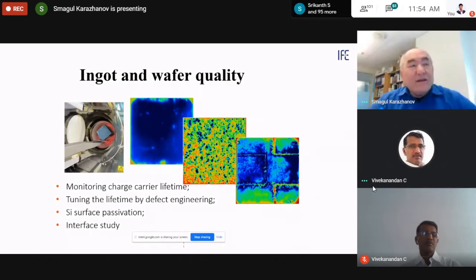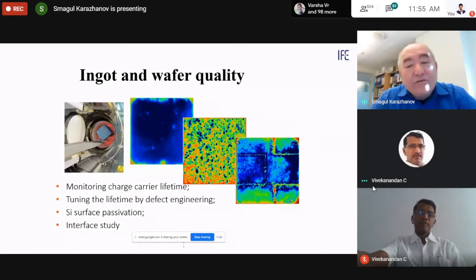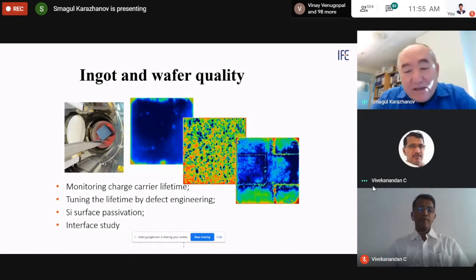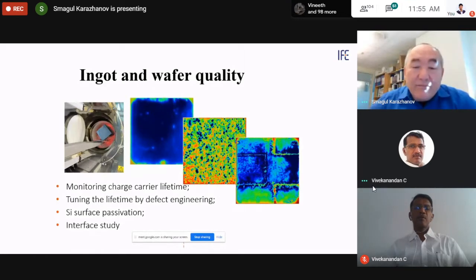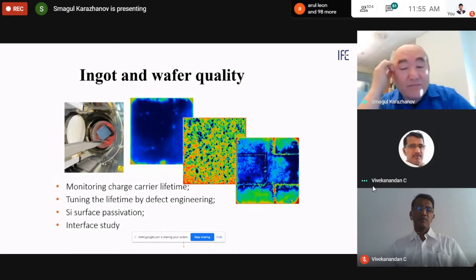However, the point is this good P-type conductivity is achieved by doping with boron, and if so, oxygen likes to enter into that silicon, whereas in phosphorus doped silicon there is less oxygen. And when P-type boron doped silicon is used, oxygen forms a complex with boron, the BO complex, and that complex is metastable, and that reduces charge carrier lifetime. Because of that, many companies, some 3 or 5 years ago, were producing P-type monosilicon, but then they stopped it and started to produce N-type, because there was a question how to suppress, how to avoid formation of the boron-oxygen complex. If it's formed, how should it be decomposed? That was and that is a big problem.